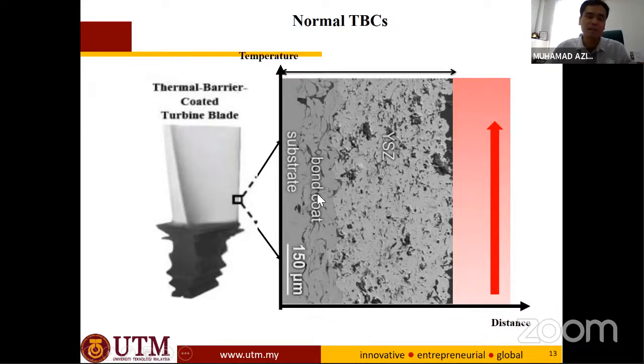So we need to put something to reduce the coefficient difference between the ceramic and the metal. What is widely used in industry is a metal coat that has ingredients of the substrate, for example nickel, chromium, aluminium, yttrium. There is nickel and aluminium from the substrate, and we also have yttrium as an element present in the bond coat, so we can synergize these two elements. This bond coat must be in between the substrate coefficient of thermal expansion and the ceramic thermal expansion, because our purpose is to reduce the coefficient of thermal expansion. So, that's my response.